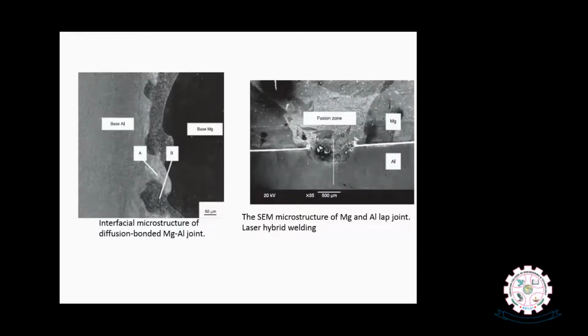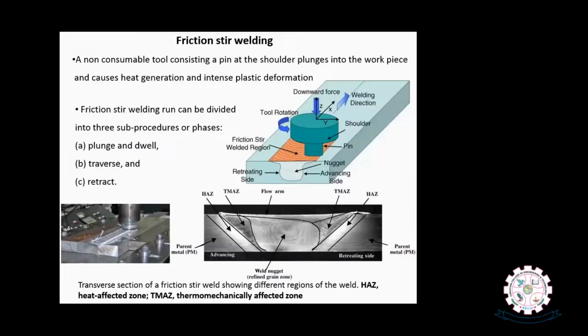Okay, so when we mix magnesium and aluminum dissimilar metals through welding, at the interface we will certainly find formation of some intermetallics. The formation of these intermetallics in the weld joint is a big challenge because these brittle phases will dictate the quality of the weld joint. Among the available welding processes for magnesium, the solid state processes are promising. Among them, friction stir welding has been widely used for more than 20 years, in which a non-consumable rotating tool is inserted into the materials at the joint where the materials are intended to be joined.